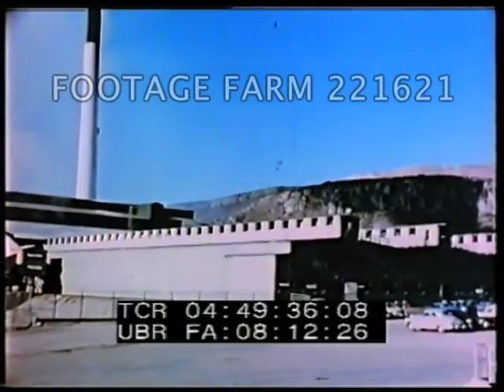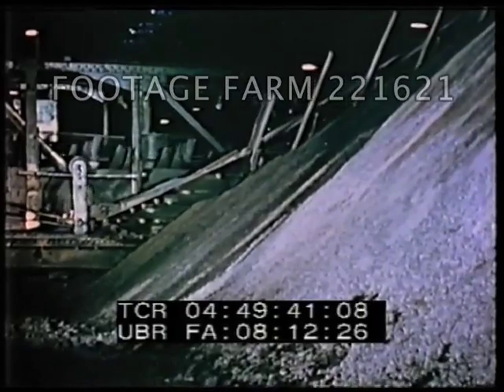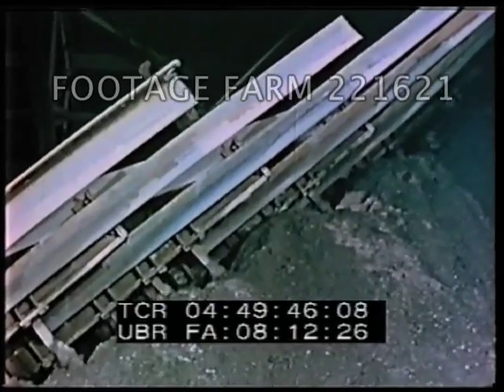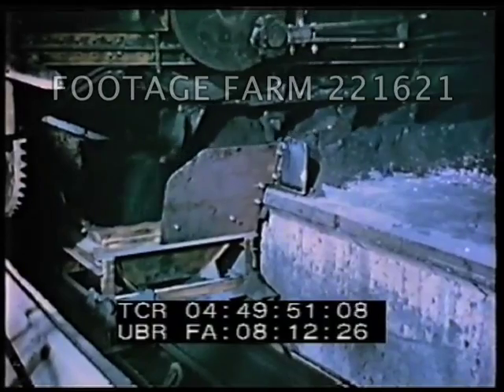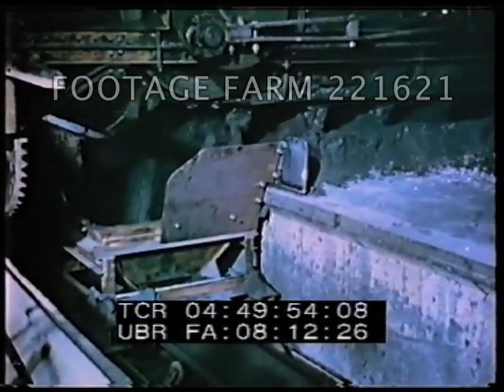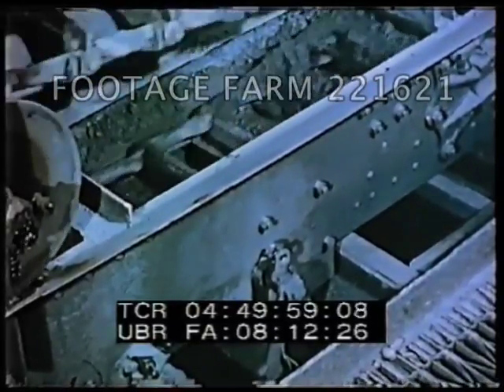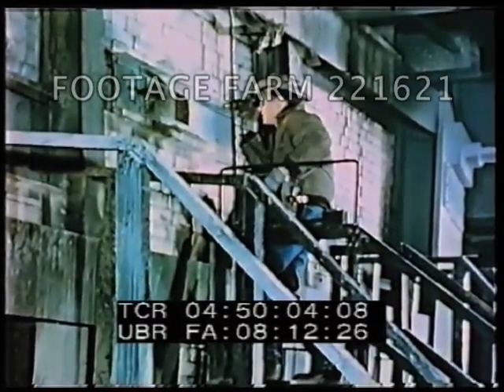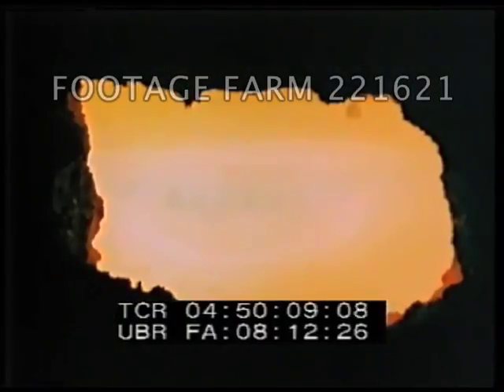In this building, known as a bedding plant, flux is distributed over huge piles of concentrate. Flux aids the fusion of the non-sulfide portion of the material into slag during furnace treatment. A special rake draws off and combines the desired mixture of flux and concentrate. The mixed charge is introduced through the top of a reverberatory furnace. The intense heat created within these gas-fired furnaces is periodically checked with instruments, including the optical pyrometer, which measures temperature by the brilliance of the furnace interior.